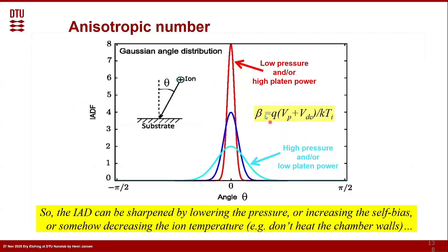Another way of increasing beta is getting the DC bias higher. So we just have to increase the self bias. That means probably the power should be a little bit higher. Another technique would be to get the ion temperature down. Some reactors heat up the walls, let's say up to a few hundred degrees, or maybe 150 degrees, and that will not help. So we would rather cool down the chamber walls, or keep them at room temperature. That also improves things, because then the isotropic behavior is less. So there are techniques to make it as sharp as possible.